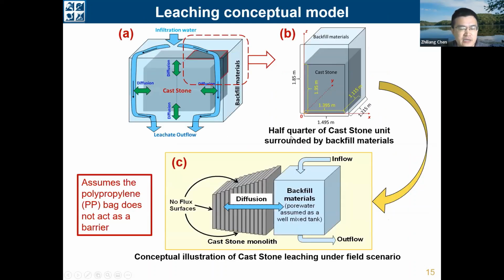And this is an illustration of the leaching conceptual model. So as you can see in Figure 8, the Cast Stone block is surrounded by the backfill material, and because the hydraulic conductivity in the backfill material is about 6 orders of magnitude higher than that in the Cast Stone, we assume the infiltration water is primarily flowing through the backfill material, and during the flow of the water, the contaminants will diffuse from the Cast Stone into the pores of the backfill materials.